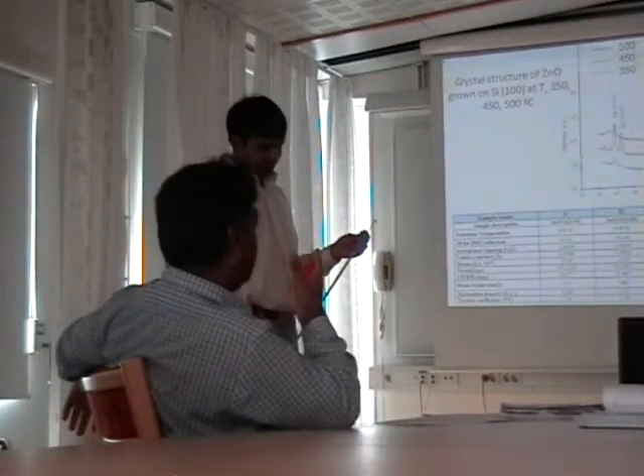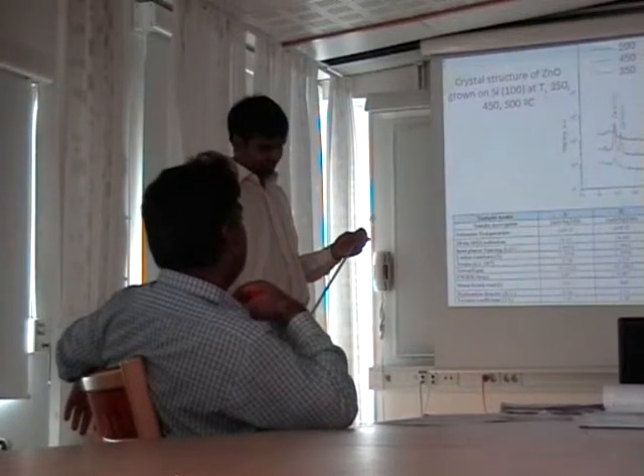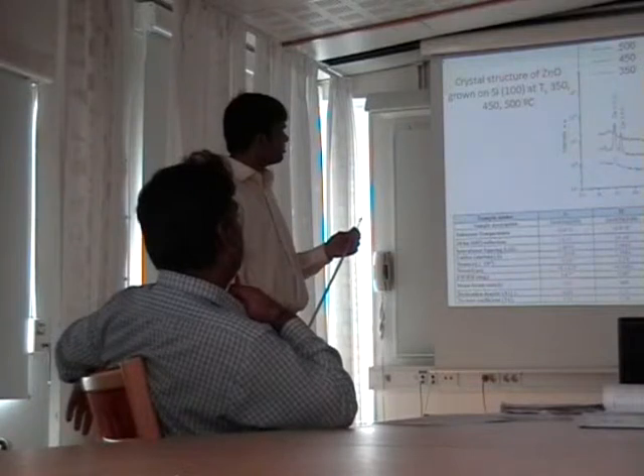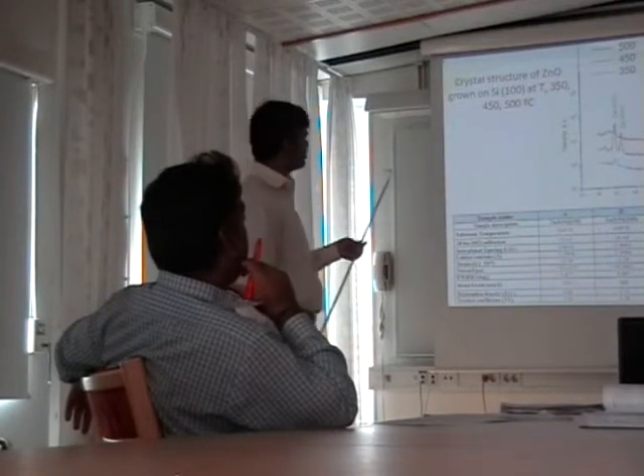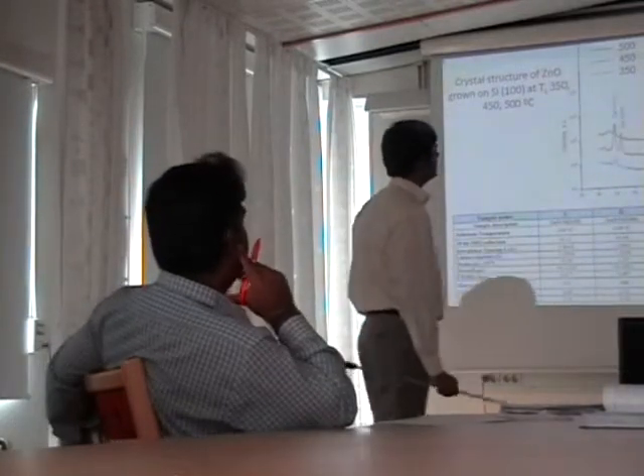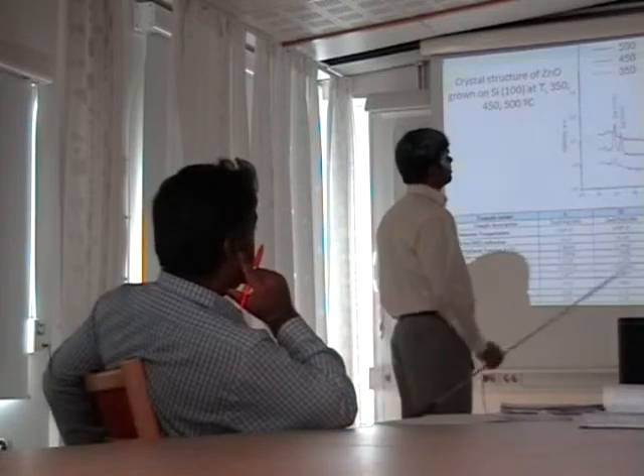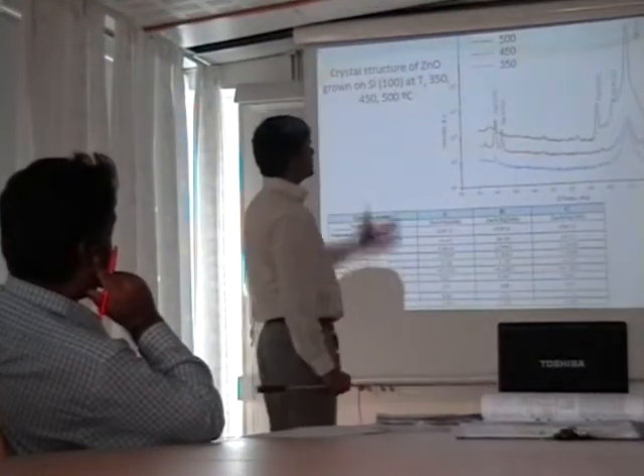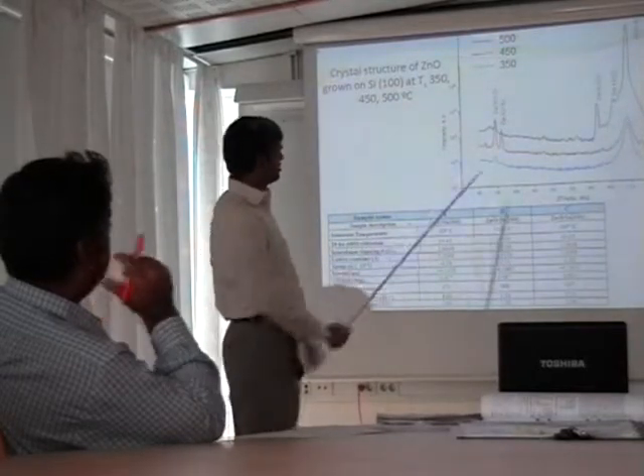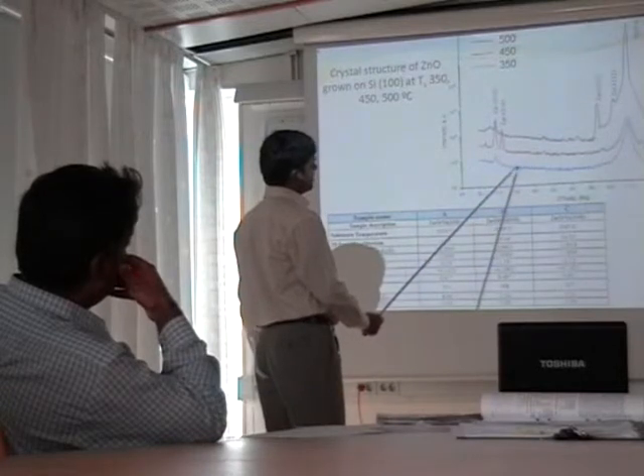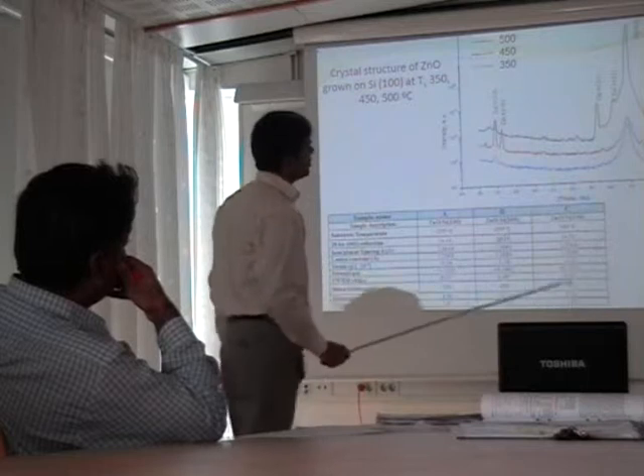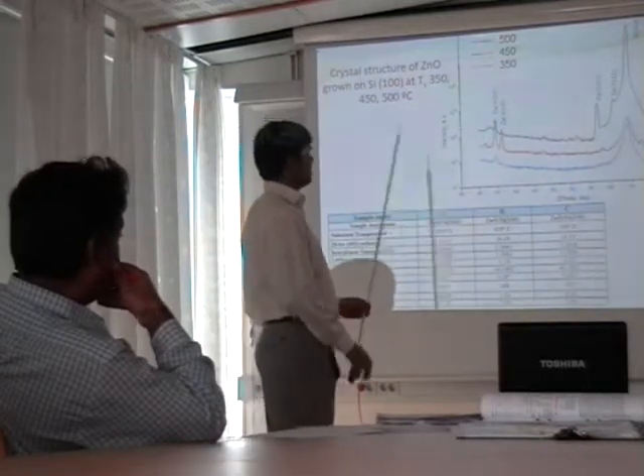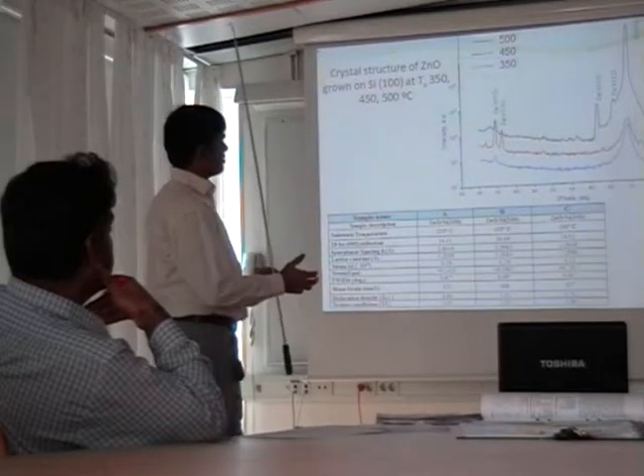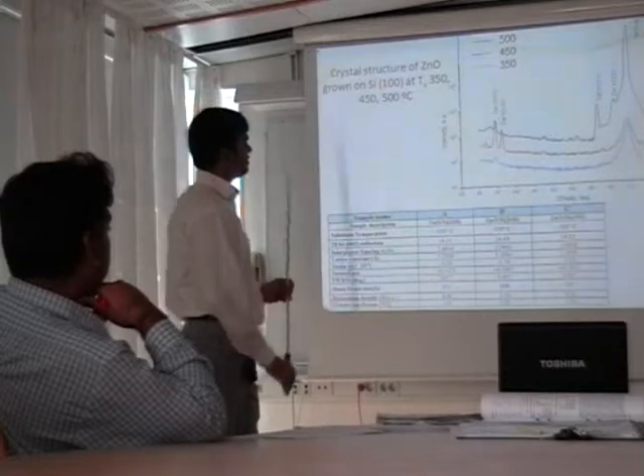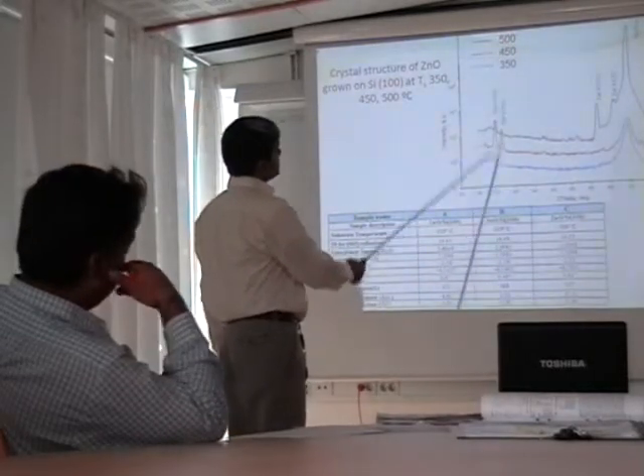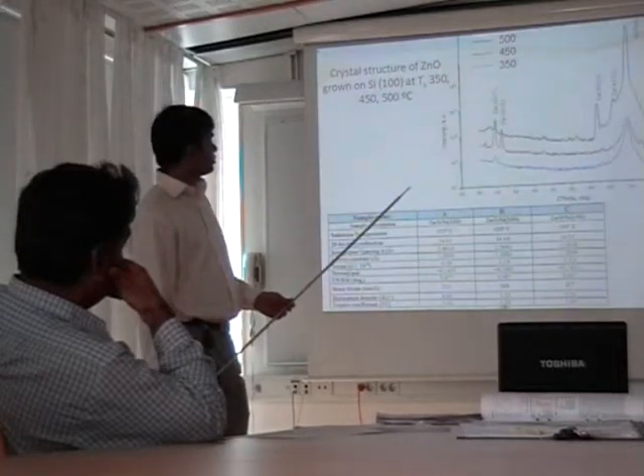First, I have a question regarding this XRD spectrum. We can see one additional peak in the case of 450, the second peak, zinc oxide 101 peak. What does this mean? This means the film shows a polycrystalline quality, having these two peaks with the increase in temperature. And here you didn't see any peaks at 350 temperature. They show closely related to amorphous. With increasing temperature, the adatoms get a specific place, and they enhance these peaks of 002.